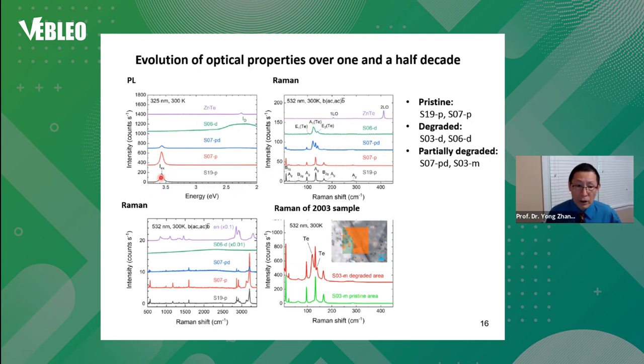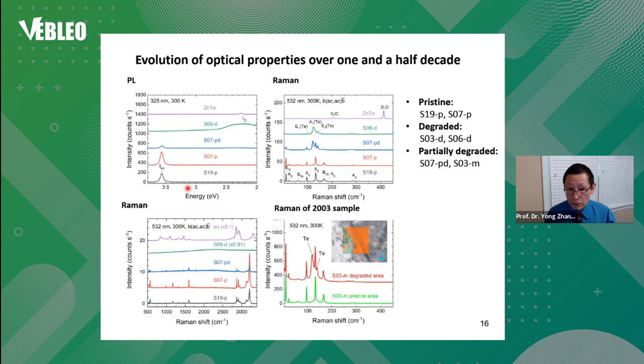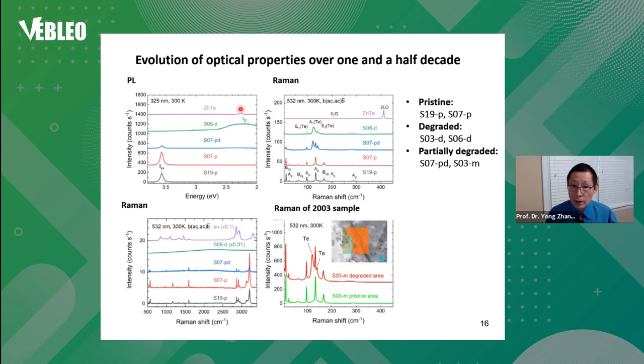For the newly made sample, we see only one excitonic emission with no below-bandgap defect transitions. The 2007 samples are almost as good as the newly made ones — those are 12 years old. Some are slightly degraded with weaker intensity, and some are severely degraded where you see mid-gap defect emission. For comparison, zinc telluride has an emission at its bandgap around 2.3 eV.